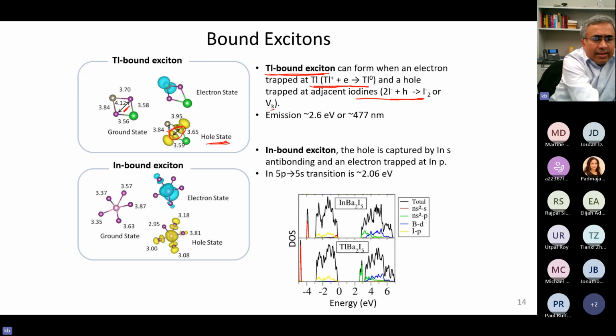They shorten their bond length, and it's like an I2 minus molecular ion, if you will. That's famously called a VK center. So the VK center will have the trapped hole. The electron will be trapped at the neighboring thallium P site, and those two together will create that bound exciton, and that bound exciton is now able to recombine to give us an emission wavelength of 477 nanometer or 2.6 electron volt.